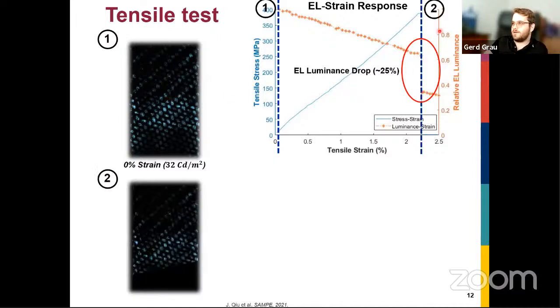And after we observe failure, you can see two things. One is here in this region, our brightness has gone down, but also at the bottom here, this complete area is black because we have a crack. So the sample has failed, and you can actually see that the sample has failed. You don't need any sophisticated sensor or monitoring equipment or anything. You can see that it has failed visually.